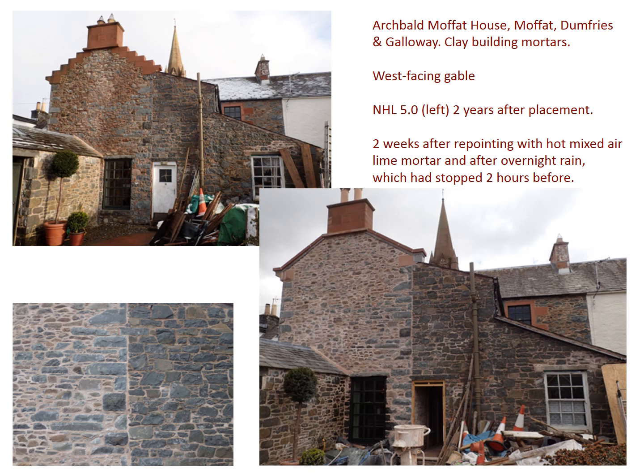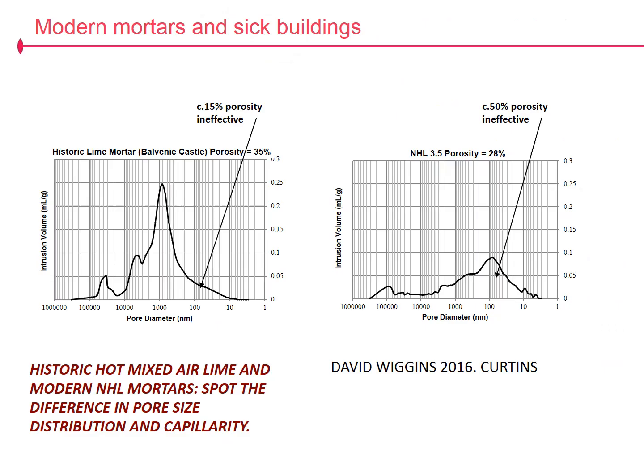The Archibald Moffat House in Dumfries and Galloway, a very wet part of the country, clay building mortars, pointed with NHL 5 2 years before the top left photo was taken. Below right and below left, 2 weeks after repointing with a hot mixed air lime mortar and after overnight rain, which had stopped only 2 hours before these photographs were taken.